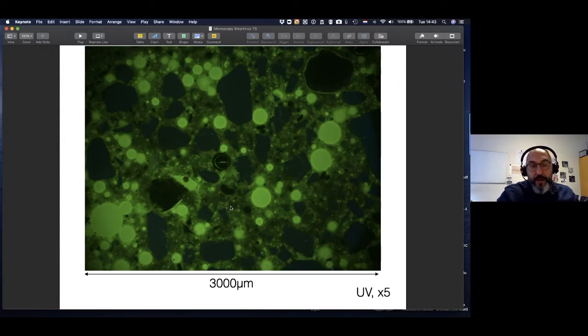On the other hand, sometimes we want air in our concrete, and we call them air entraining. So we use air entraining agents, special chemicals, to drive all these tiny spherical air voids in our concrete, so that you see they are super small compared to entrapped air, but also well dispersed. The whole idea here is to improve the durability of our concrete when the frost kicks in and the ice front reaches these air voids. So the water inside my capillary pores can escape to an escape vessel. And that's the whole idea, so that the hydraulic pressure will be released. That's the reason the amount of these air voids and their positioning, their spacing, as they say, is extremely important. And with microscopy, you can very well characterize and understand if your concrete is, let's say, frost immune or not.